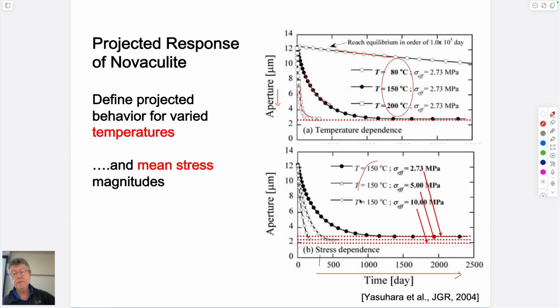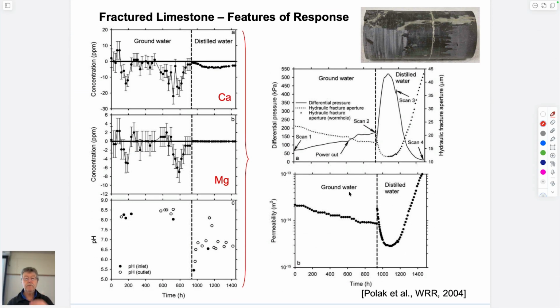Likewise, you could hold constant the temperatures, but change stresses. And if you do that, as you increase the stresses, then you see that the rates increase a bit, not as quickly as they did before, just a small change. But as a result of changing these stresses, the closure that you get becomes larger with increasing stresses. So you don't change the rate at which it occurs very much as you change stress, but you do change the end magnitude of the closure of the fracture. And so you can use that in a model to represent the behavior in a reservoir, which was part of the reason for this. Actually, the work was funded as a geothermal project.